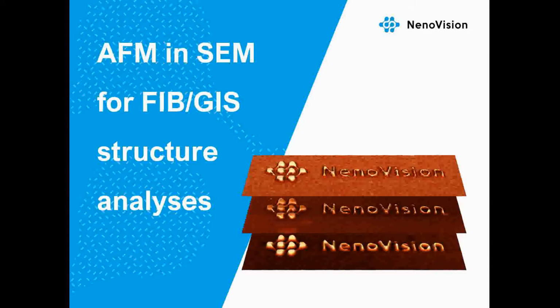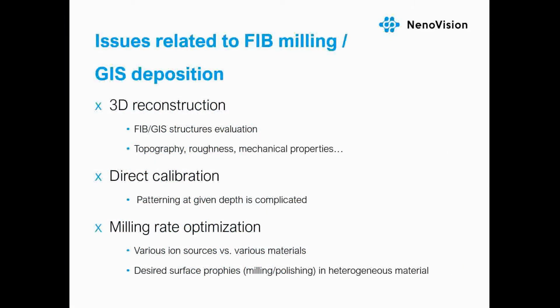The development of combined focused ion beam and scanning electron microscopes has enabled significant advances in the characterization of 3D structures of materials. However, as any technology, FIB and GIS systems come with challenges, partially arising from the limitations of SEM systems. So although focused ion beam surface modification is very precise, it is not possible to accurately determine the depth of the sputter structure, as the sputter speed depends on the chemical and crystallographic composition of the sample. This issue gets especially pronounced with heterogeneous materials.